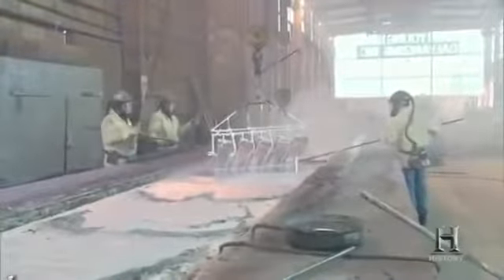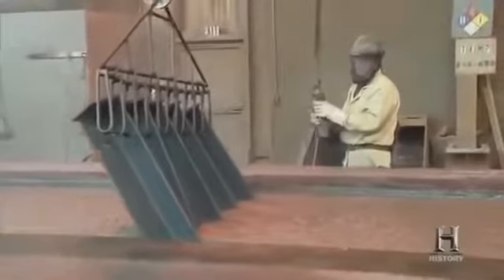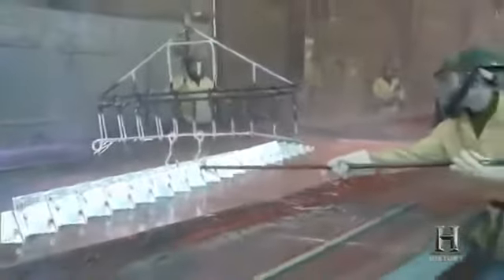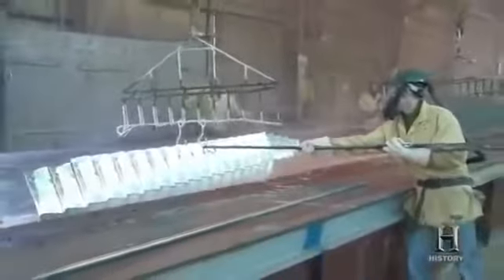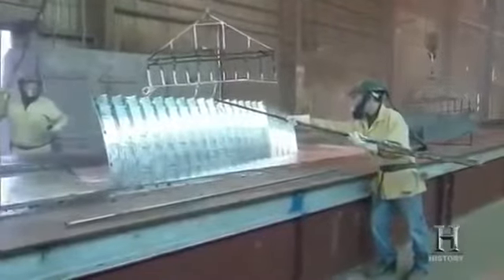Here at Young Galvanizing near Pittsburgh, the galvanizing kettle is 48 feet long, 5 feet wide, and 8 feet deep, big enough to submerge the largest pieces of steel. The steel is immersed in zinc until it reaches a bath temperature of 840 degrees Fahrenheit. The zinc and steel actually form a metallurgical bond, an alloy that will resist rust and corrosion for many years to come. Zinc has thus fulfilled its role as the great protector.